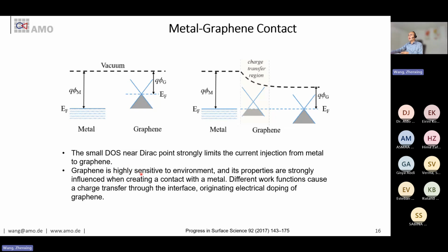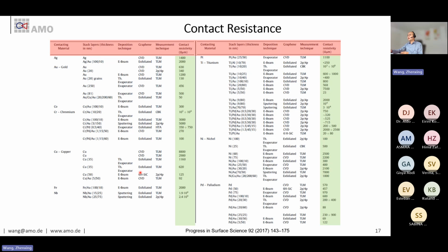That is also the reason why it makes the contact between graphene and metal so difficult. So people put a lot of effort into it, like using different metals, different thicknesses, and different deposition technologies, e-beam, evaporation, and so on. Also, the material can be from CVD or exfoliation or other materials from silicon carbide. And the measurement method also plays a role here. So in the end, you see basically all the values are available.